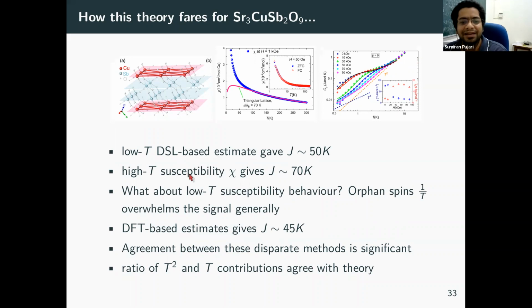Whereas there's another way of analyzing the data using the high temperature susceptibility. This is completely in a different part of the parameter regime. That gave us a 70 K dominant energy scale. This agreement was quite significant because these numbers are coming from two different regimes and have nothing to do with each other in some sense. In one regime, quantum fluctuations have completely taken over, whereas on the high temperature side, it's all thermal fluctuations. Additionally, DFT-based estimates also gave agreeing numbers, and we can also confirm some more detailed agreement with theory in these linear and quadratic contributions to the specific heat.